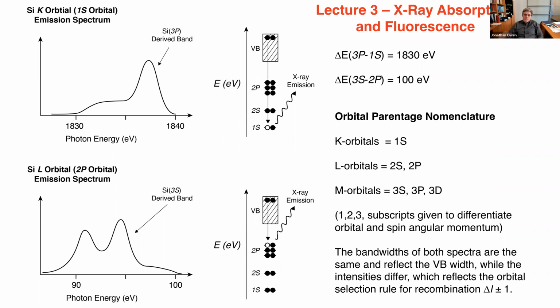character. And this makes sense if you think about the splitting of the 3s and the 3p levels of the atom. S is below p because it penetrates the nucleus more effectively. So looking at the relative peak shapes and intensities of these 2 transitions allows you to analyze the angular momentum of the orbitals at the bottom and the top of the valence band.